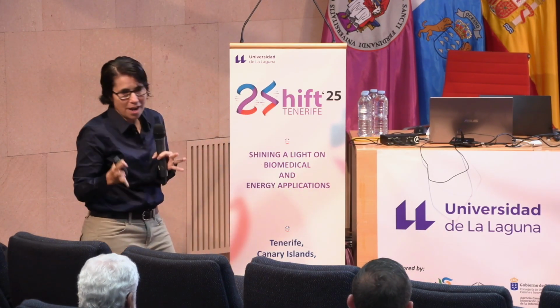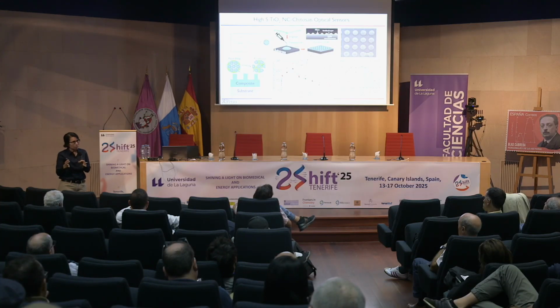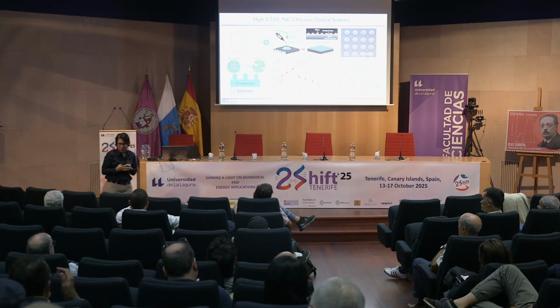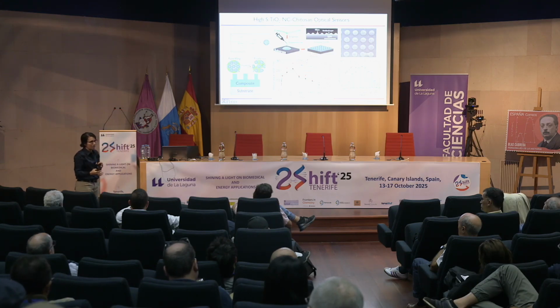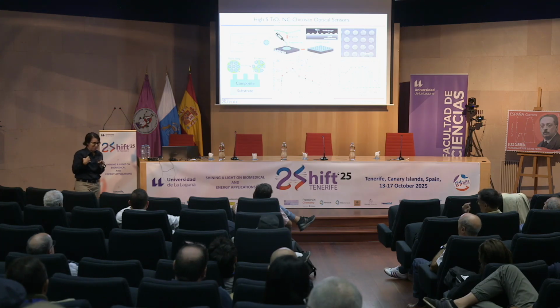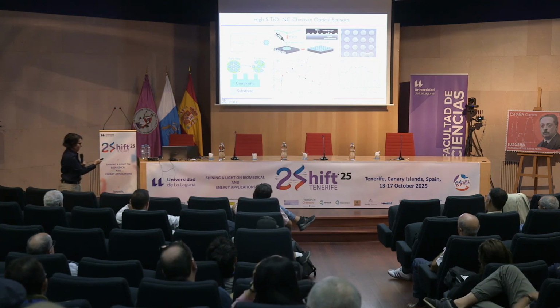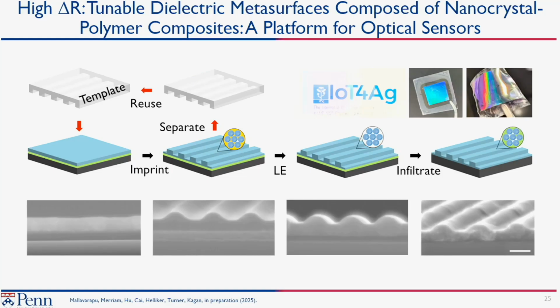The one thing is that we so far had high Q and high S, but the reflectivity in our first structures was kind of small, and it was hard to see in real environments when we sent the robots out. Perfectly fine in our spectroscopic techniques in our lab, but that wasn't the challenge where we had it. So the most recent structures that we're just finishing some work on now, we actually switched to using UV curable titanium inks. You can imprint into those. Underneath that, we put a layer of this chitosan, and after we imprint, the imprint ink actually has a whole bunch of organic molecules to make it UV sensitive. So we do this ligand exchange process, and it removes the organic components, which we can follow using IR spectroscopy, and makes a nanoporous material.